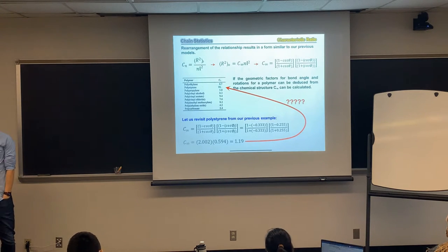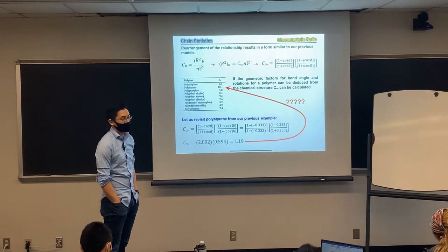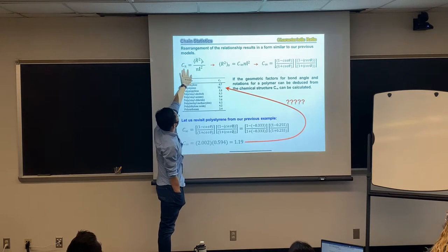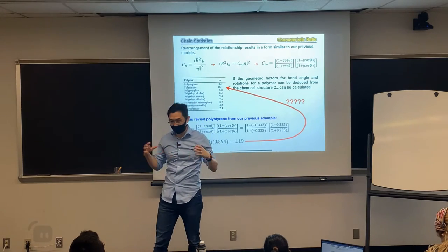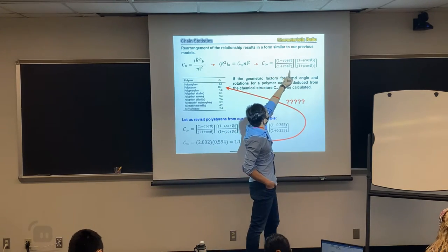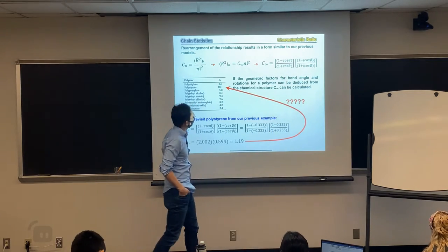So how do we understand characteristic ratios for a wide range of polymers we know? So let's go from the top. We know the characteristic ratio is basically given by here. And I like to explain in layman's terms, that's like the expansion ratio for your polymer coil, how much its size is being expanded, right? The higher the C infinity, that means your polymer is more expanded or swollen compared to a free joint chain. And this can be easily defined by theta and phi angle, coming from the two other models we talked about. Okay, what's the significance?